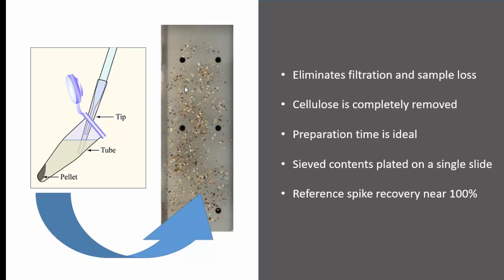You can do this under a stereo microscope as well, so you make sure you're not pulling up any of the particles in the pipette. Once we've pulled out all that material, we add just a drop or two of methanol. We then remove the pellet and plate it out on the microscope slide.